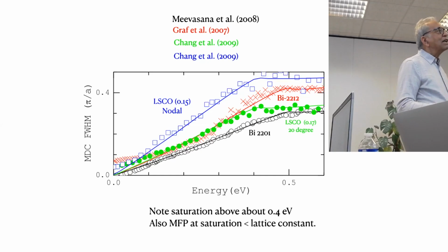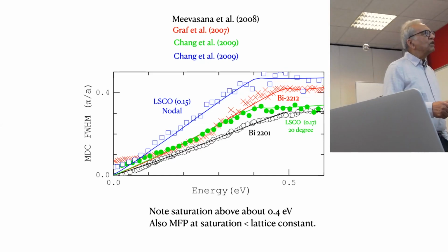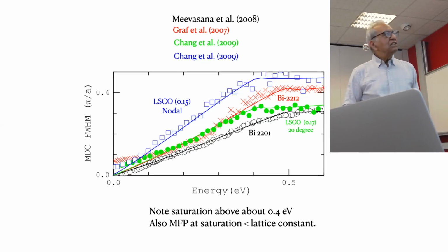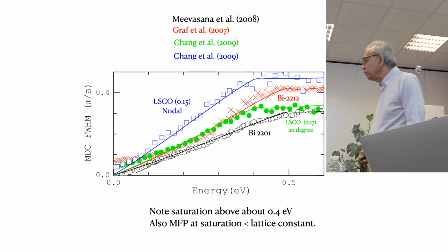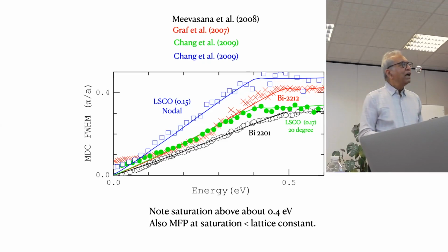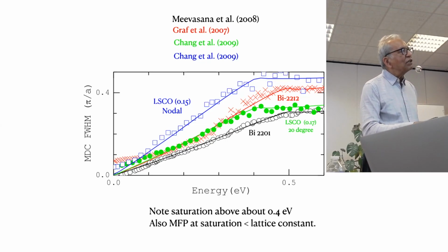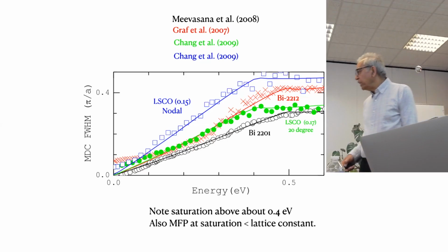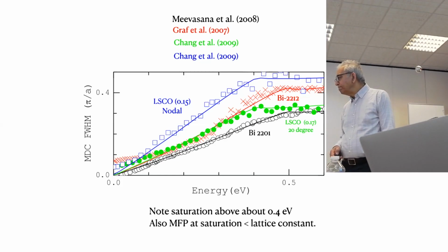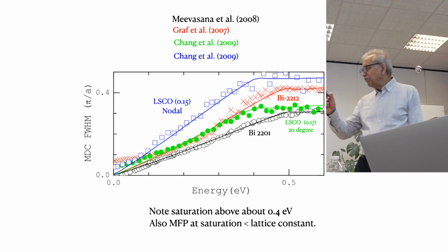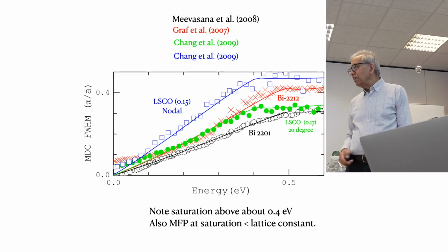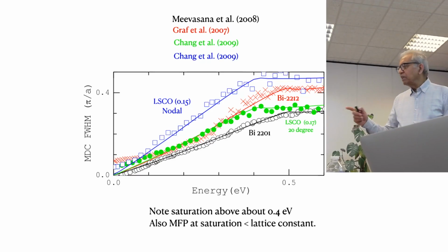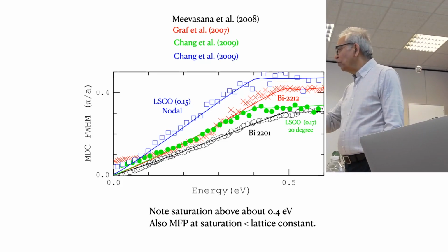Very good point. I think I have written here. For bismuth 2201, bismuth 2212, it is at the optimal doping and in the nodal direction. For lanthanum strontium copper oxide, the optimal doping is about 0.19 or 0.20, and it's 0.15. And this is lanthanum strontium copper oxide 0.17, and not the nodal direction, but 20 degrees away from the nodal direction. Okay, and the resolution of the experimental data gets worse as you go away from the nodal direction because of the experimental background, but you typically find that there is less than a factor of 2 difference in the slope going across.